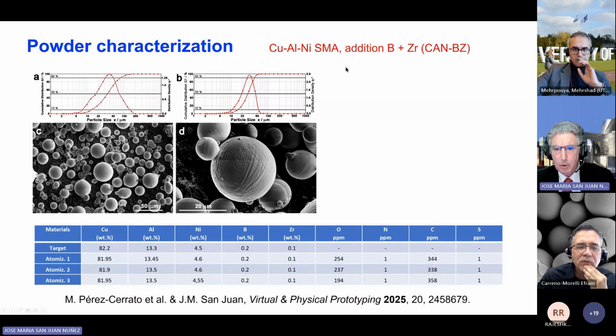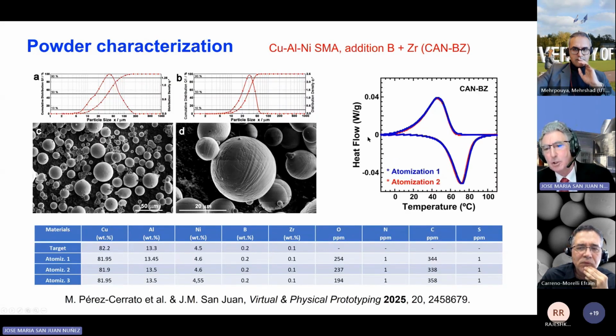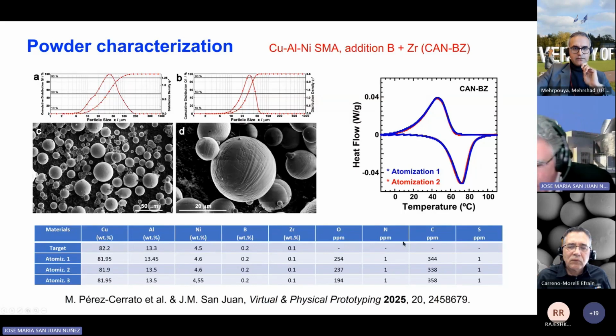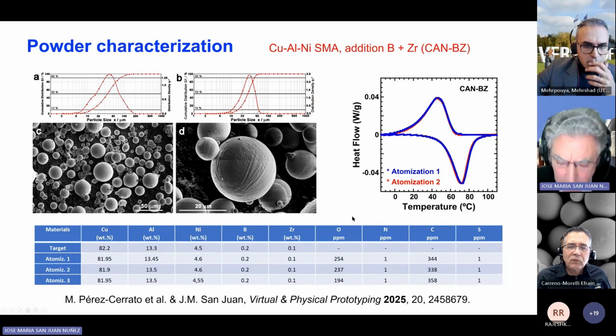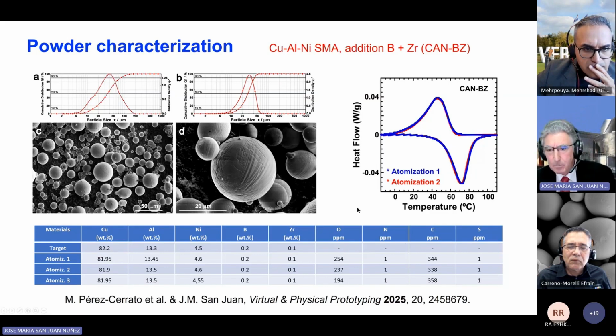So the reproducibility of the atomization can also be seen if we perform a differential scanning calorimetry on the powders obtained in each atomization. You can see here the comparison between the thermograms of the powders from atomization 1 and atomization 2, and really the thermograms are absolutely superimposed. So the reproducibility from one atomization to the other is quite perfect.